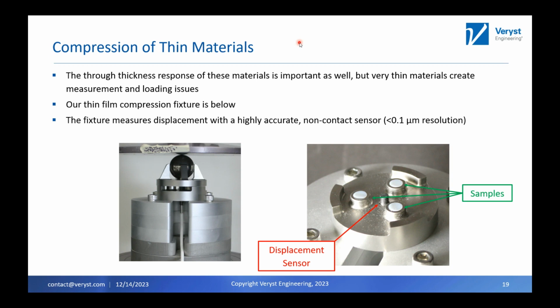So we will add lubrication in there. This 6 millimeter sample size, we kind of choose based on what we're trying to get. If we want to go to higher strains, we might go to an even smaller sample to get a better aspect ratio. And when we do this on foams, we don't worry as much about that because they have a much lower Poisson's effect, and therefore that effect is much less pronounced. So the answer is yes. I always worry about friction.